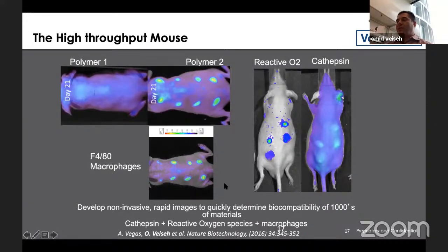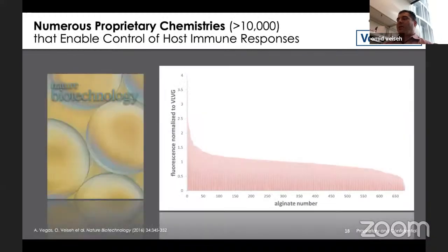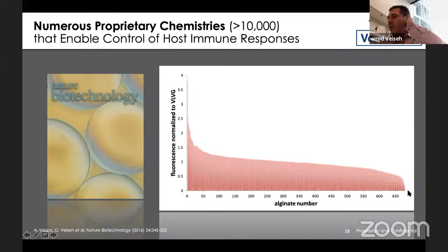And so where we don't see signal, we do correlate that with long-term improved outcomes in terms of fibrosis. This is actually the results from a subset of the screens that we did. Each of the materials is identified by a number. So this is formulation 1 all the way out to, in this case, we did 774 different formulations.